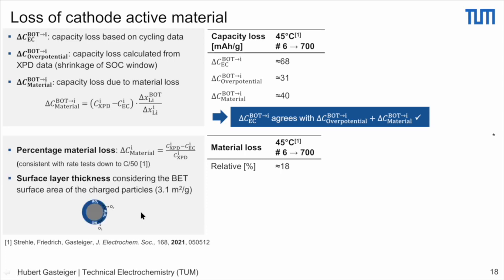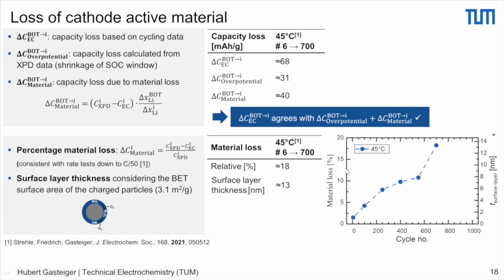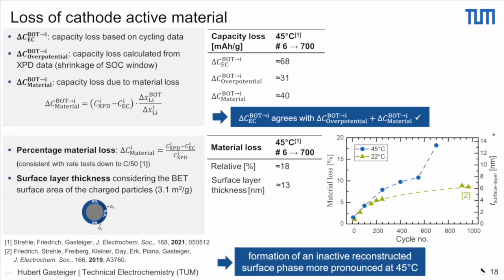If that were true, the estimated thickness of the surface layer, sort of like a core shell particle, if you want, based on the BET area of a reasonably cracked material as we measured before, would be about 13 nanometer. So this is reasonably consistent with what people find in the literature. If we plot this here, this is the relative material loss. This would be the calculated surface layer thickness over these 700 cycles. You see it sort of continuously increases. And if we compare this to previous data we had done with exactly the same material using the same process, but at much lower temperature, then you see that higher temperature actually enhances this effect. And so what we can see is that we have a formation of an inactive reconstructed surface phase that is more pronounced at the higher temperature.